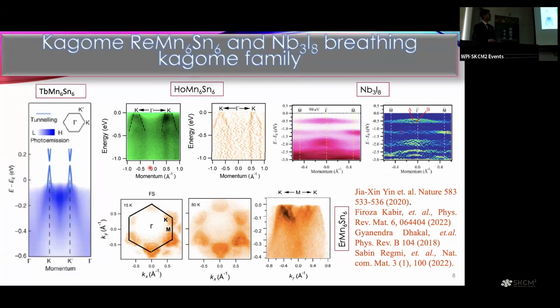Here, the bands are slightly broad because the measurements were performed at around 270 Kelvin, because this is a semiconductor and there is a lot of charging at low temperatures. But you can at least see there are multiple flat bands in this electronic band structure.